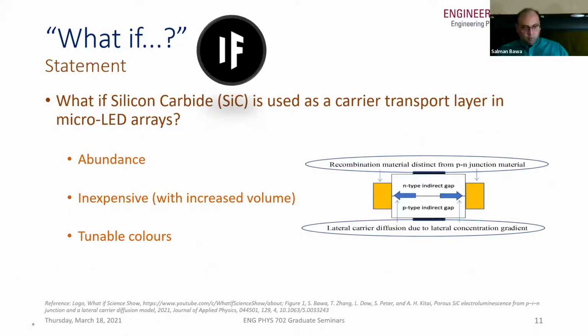So our what if statement was, what if we try to use silicon carbide as a carrier transport layer in micro LEDs? And the reason why we are thinking in this direction is because silicon carbide comprises silicon and carbon, which is in abundance. It would be inexpensive with increased volume production, and the fact that it can have tunable colors.